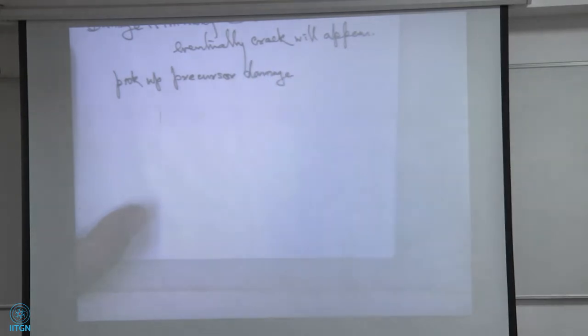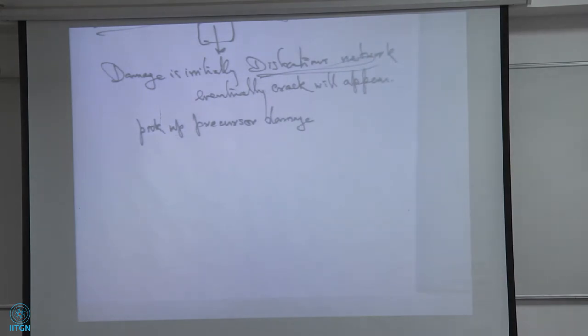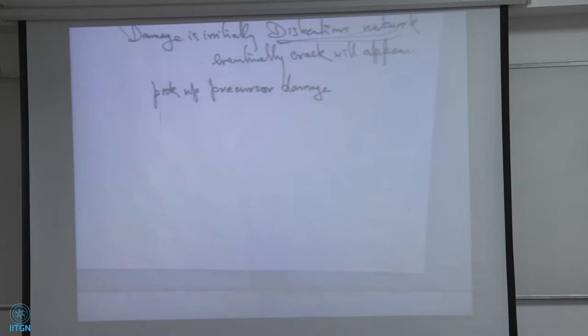Our goal was to pick up the precursor damage. Precursor damage, because before the crack forms, the dislocation networks are forming, and also the temperature of the sample is rising. So we had a very sensitive thermal sensor, a delta T sensor. It has to be very, very sensitive. So some of these thermal sensors pick up the thermal energy.